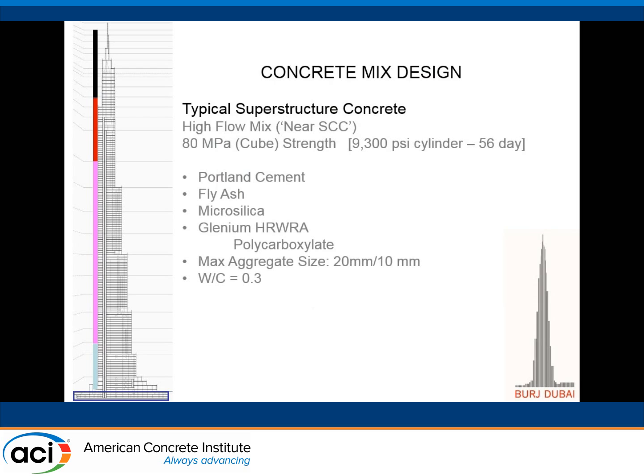Again, it was another one of these what they call bi-mix, which is fly ash and Portland cement, supplemented with microsilica for strength, also for lower permeability, and then a high-range water-reducing admixture with a maximum aggregate size of 20 and 10 millimeter blend, water-to-cement ratio target of about 0.3. So again, you don't see the viscosity modifier because although it was a high flow, it was not self-consolidating concrete.